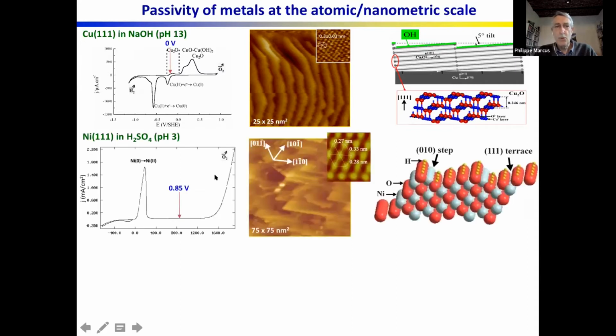What I just showed for copper was also observed for nickel, where you see in the passive range for nickel, but now it's in acidic solution, whereas for copper, it was in alkaline solution. You have a highly crystalline passive oxide, the model of which is shown here, where you have terraces of the oxide and steps, and you have this OH layer covering the surface. And here again, there is a slight tilt of the oxide that is accommodating the mismatch between the substrate and the oxide. And this again is provided by nature to minimize the interface energy, and the surface energy is minimized by the presence of OH group.